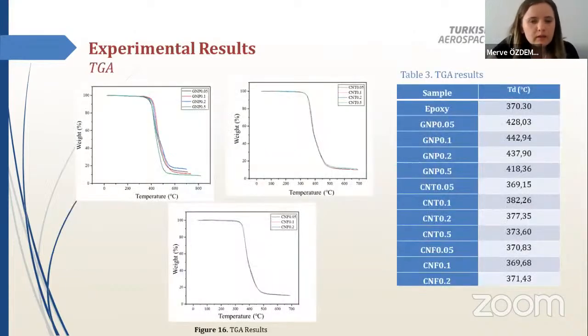Now we can examine the TGA results. When the TGA results were examined, it was seen that the GNP additive increased the decomposition temperature of the resin. The highest increase was seen in the GNP 0.1 sample. However, the addition of CNT and CNF didn't increase the decomposition temperature of the resin much.